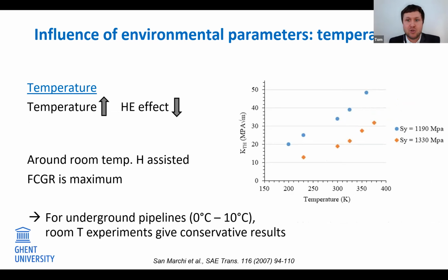At temperatures lower than room temperature, the diffusivity of hydrogen is too sluggish to substantially accumulate at traps. At high temperatures, hydrogen mobility is strongly enhanced and trapping is diminished, and detrapping is also facilitated. For instance, for underground pipelines operating between 0 and 10 degrees, room temperature experiments can give you conservative results.